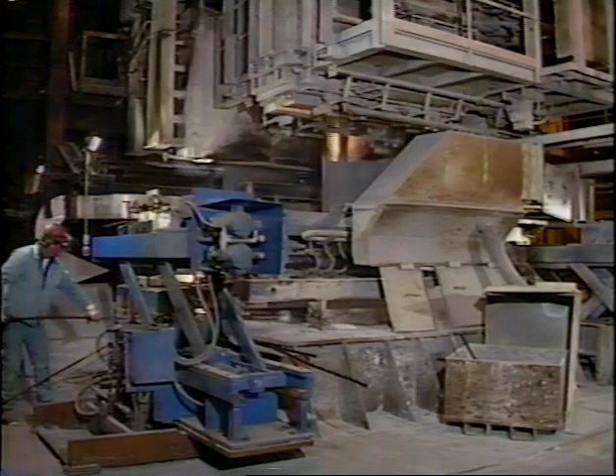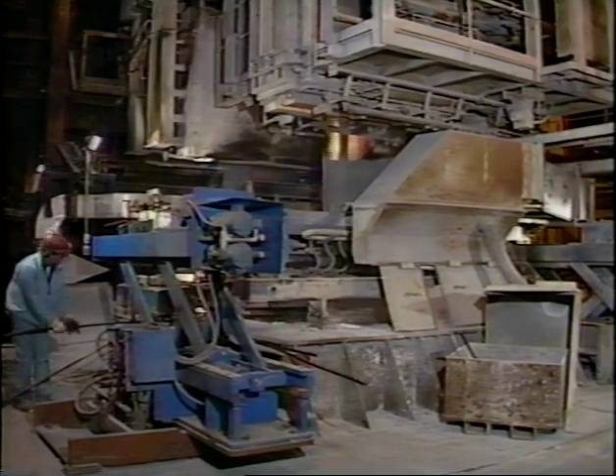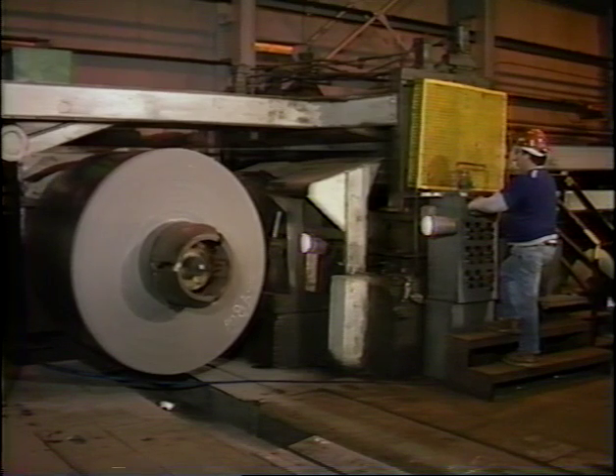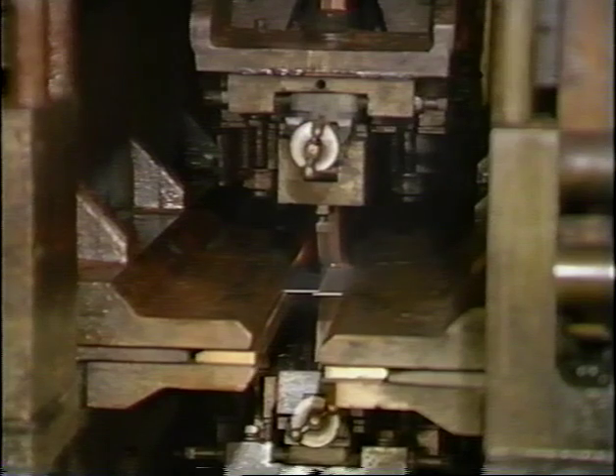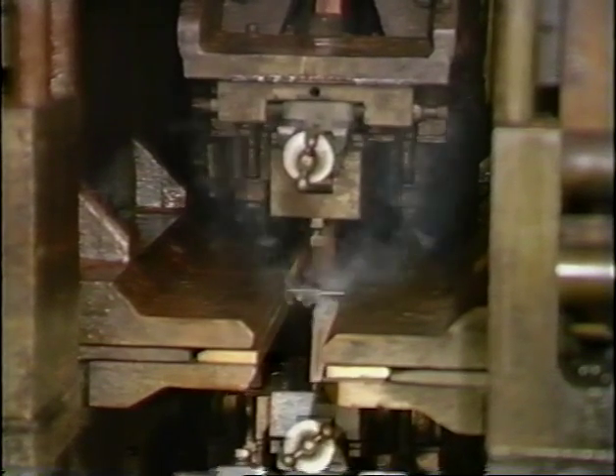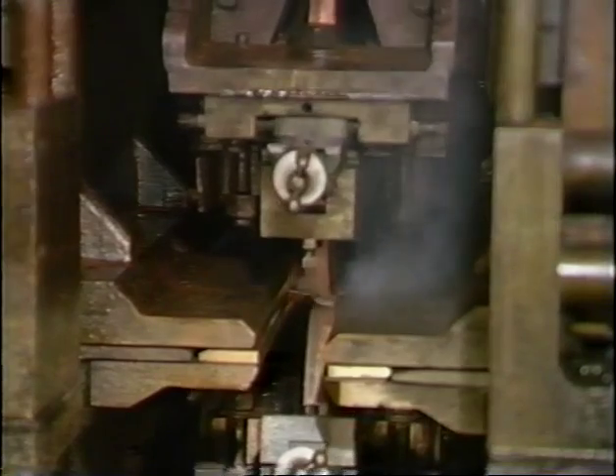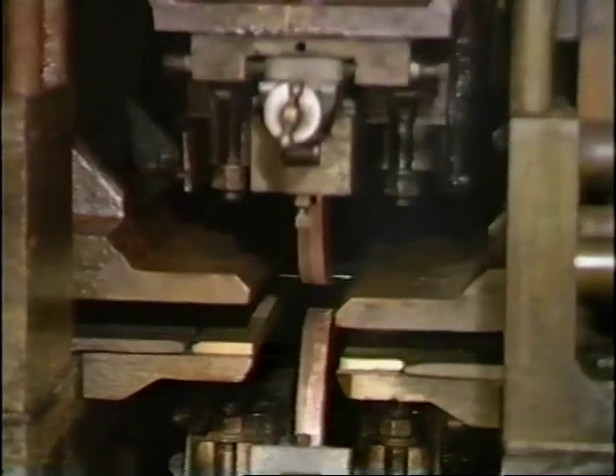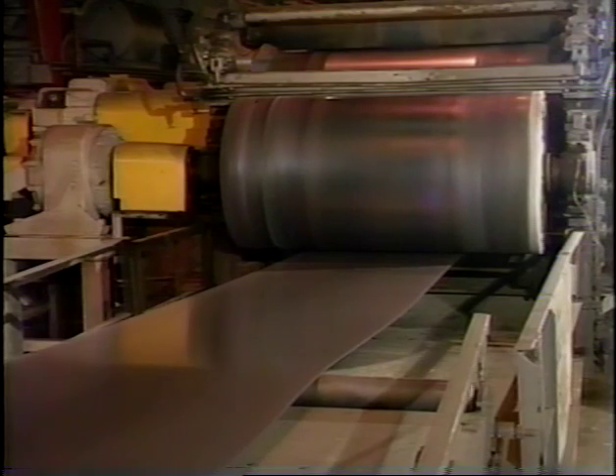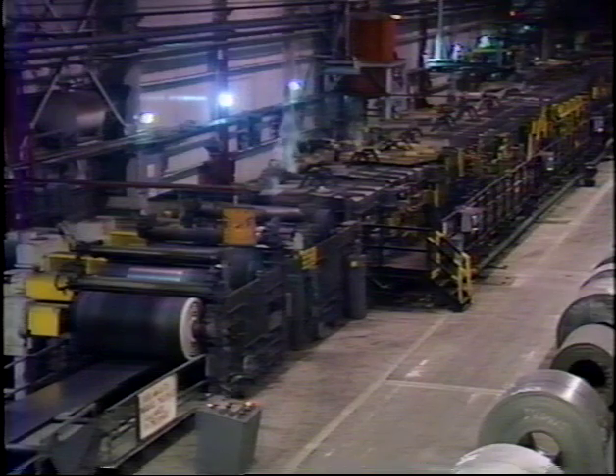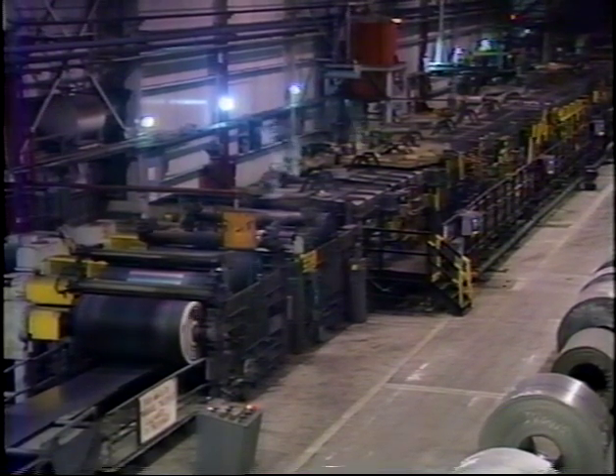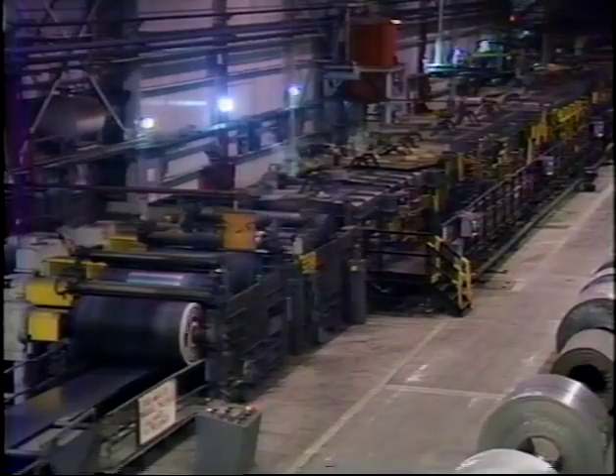Uniform coating thickness is the key to top quality galvanizing, and everything we do in the galvanizing mill is aimed at ensuring that uniformity. 2 entry reels provide a steady supply of steel, and a lap seam welder joins the coil ends to keep the steel supply continuous. When the entry end shuts down to make a weld, strip accumulated in a loop storage car feeds at a constant speed through the cleaning section and zinc pot. The strip is cleaned in 3 alkali tanks and an acid tank. It is coated with flux, then dried and preheated in a series of ovens.